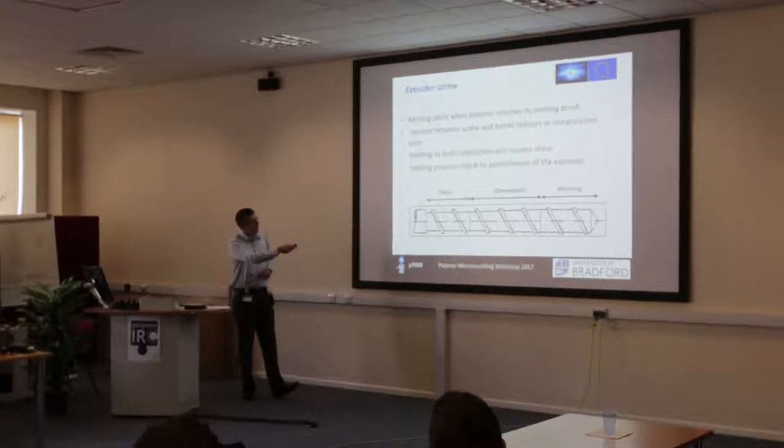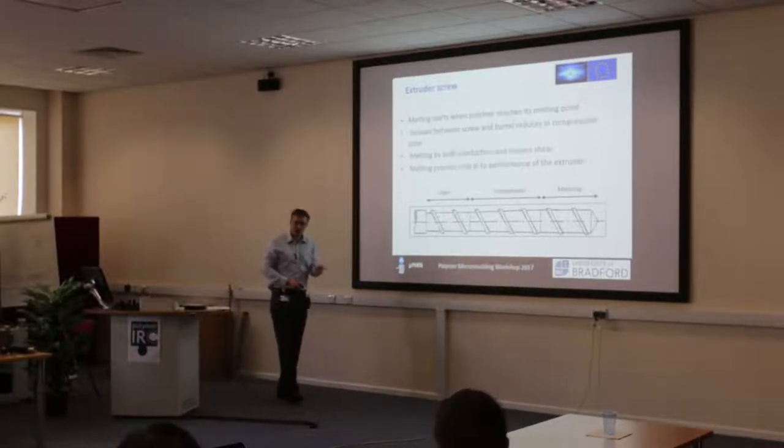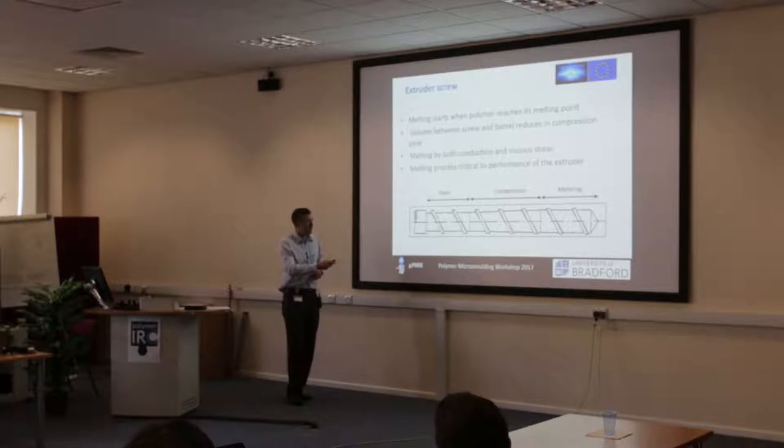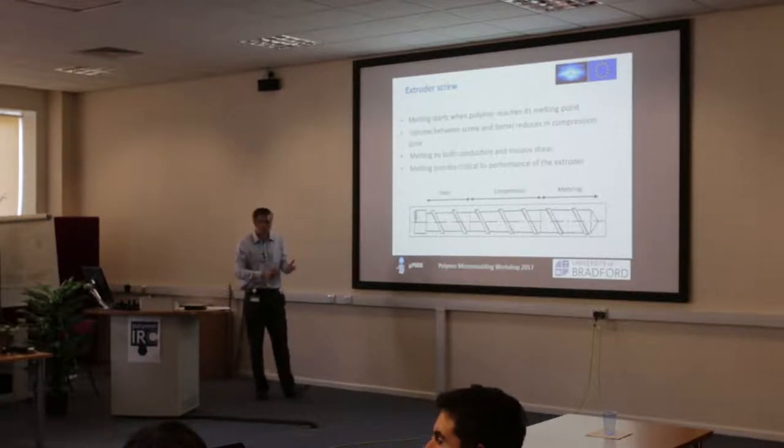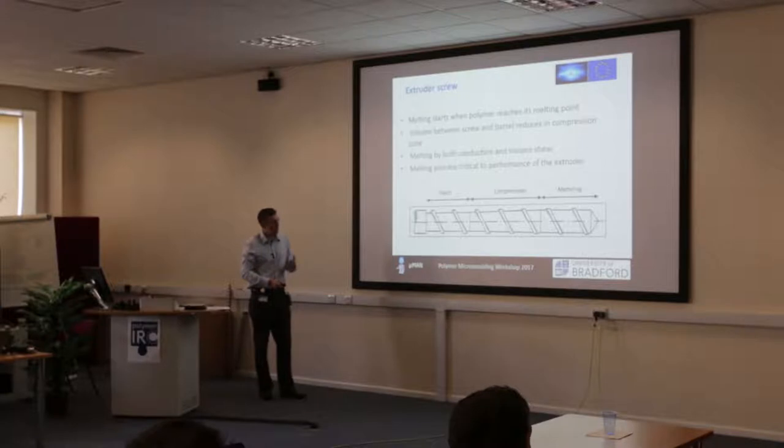The melting in the screw is by two mechanisms. It's via conduction from the barrel wall and from the screw itself, because the screw will heat up as well. Although we don't apply any heating to the screw, if it sits in a heated barrel, it will heat up. So we get conduction from the barrel and the screw.